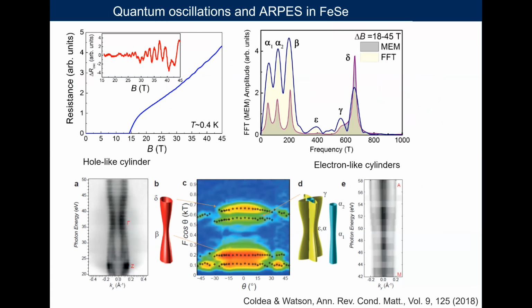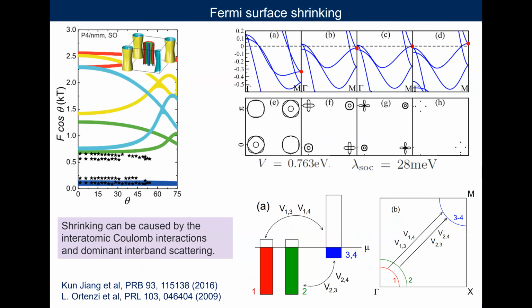We also measure quantum oscillations. So these are resistivity versus magnetic field at very low temperature. We show the oscillatory signal. This signal is Fourier transformed. And then all our data as a function of angle are plotted in this color plot. So what is this telling us? If we have a cylindrical Fermi surface and we plot F versus cos theta, we have a branch which moves like this. If it's a minimum, it should move slightly up, and the rest of the branches should come from other pockets. On the left and right are the kz dependence ARPES data showing that our pockets are quasi-3-dimensional, and we are likely to have a hole and an electron and potentially another small electron pocket in iron selenium at low temperatures.